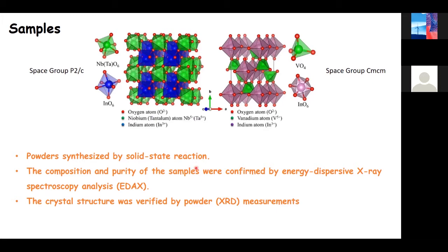So as you can see here, and as I showed before, two of these compounds, the indium niobate and the indium tantalate, will crystallize in this monoclinic structure. In this structure, we have a zigzag chain of indium octahedra and also a zigzag chain of niobium or tantalum octahedra. And in this one, we have a linear chain, which is more symmetric and is orthorhombic. We have a linear chain of indium octahedra, which are connected by corner sharing to vanadium tetrahedra. And this will be fundamental for the behavior of the material under high pressure.